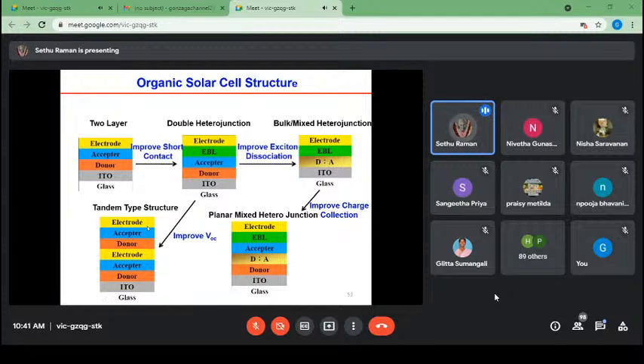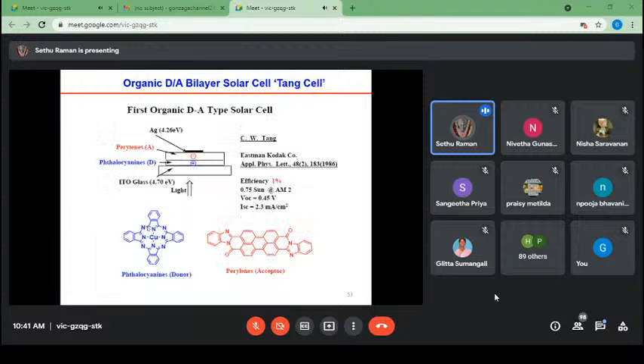So these are some organic structures used for the fabrication of organic solar cells. This is the first work reported in the literature using phthalocyanine and perylene, by C.W. Tang at the Eastman Kodak Company. This work was published in the year 1986. They achieved a power conversion efficiency of 1%, using this phthalocyanine donor and perylene acceptor.